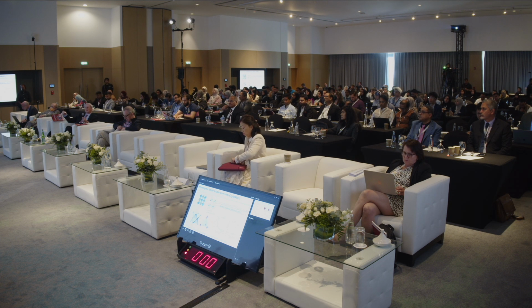Yeah, this is something we have plans to explore, but we have tried a few times. What happens is probably the more stable phase, that is the cesium-3 ruthenium-2 chloride or bromide-9, actually gets isolated. So again, yes, it's a nice comment, a suggestion. I think that phase needs to be suppressed, and then it's possible to have a 3D phase. But looking at the geometrical parameters, it should be possible. Yeah. Thank you. Thank you very much.